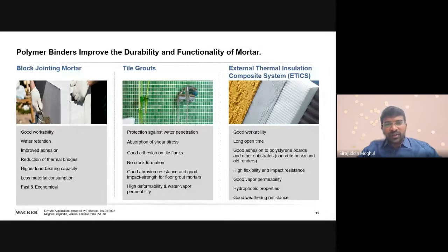So if you use polymer modified, it reduces the water absorption capacity of the grout and doesn't allow water to penetrate, so that the tiles will remain intact, and it will enhance the durability of these tiles. And the other is ETICS. We don't use this system in India.